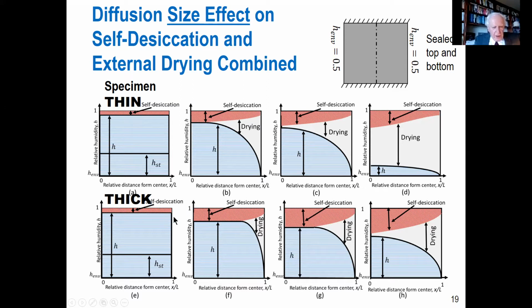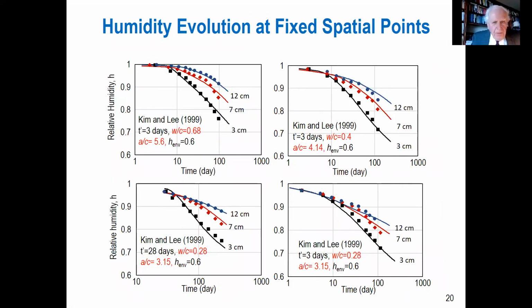Then drying starts here, then it penetrates as square root of time, roughly, and you have, compared to here, more solidification that can happen in thick specimens than in thin ones. Much more can happen here. So this is much more sophisticated. And eventually, but this can take 20 years, this can take 100 years for specimens like 40 centimeters thick, everything is controlled by drying, but not before that time. So this is a considerable complication. Size effect is major here, and you need to reconcile these two procedures to model it.